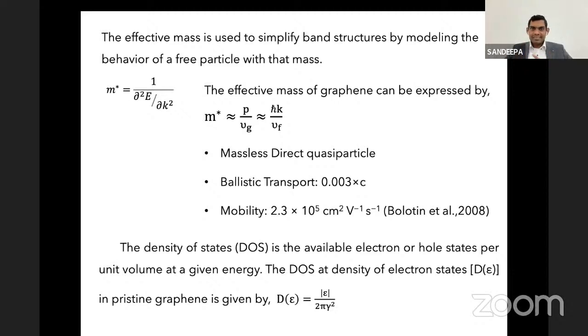Effective mass is something we use when thinking about conducting particles, which we model with some kind of mass. In most materials they show a parabolic shape, but if we move to graphene, the effective mass equation is quite different. It is a linear equation, and it also shows massless quasi-particles, and therefore ballistic transport. The speed of the electron inside the lattice can get much closer to the speed of light. It is 0.003 multiplied by the speed of light. And also we have observed extremely high mobility, on the order of 10 to the power of 5, because of this massless nature of the material.